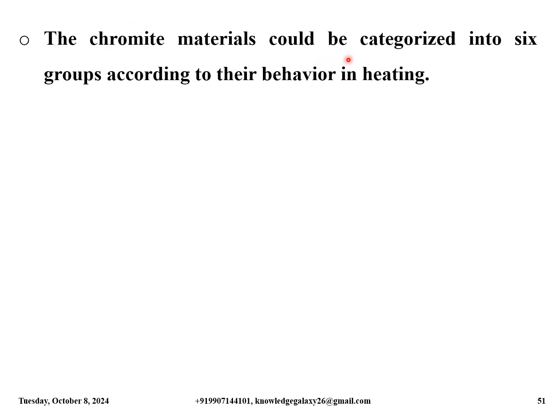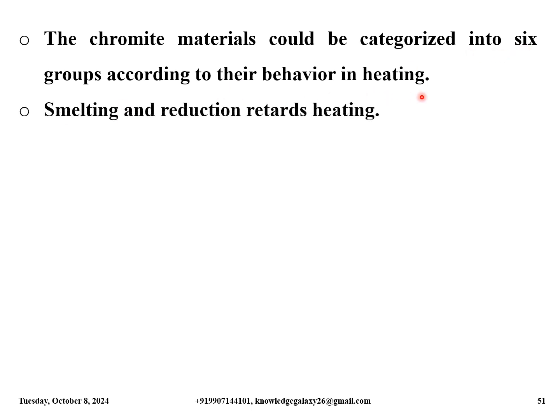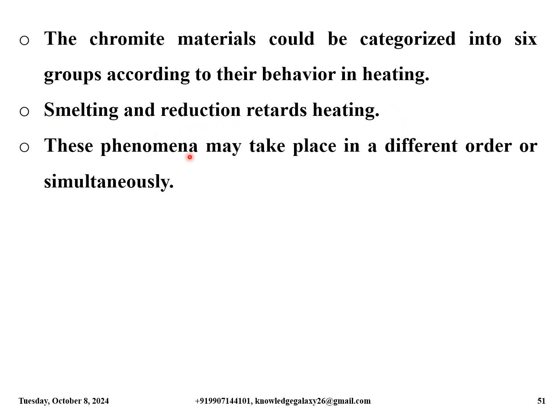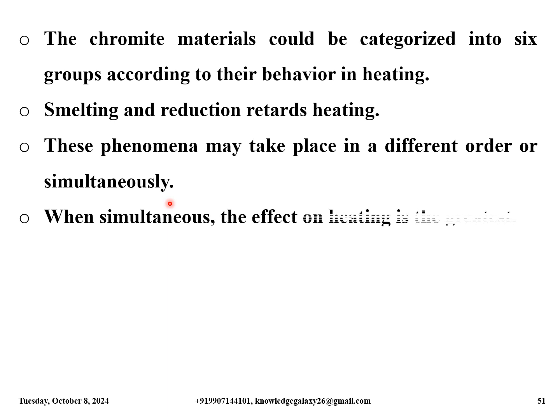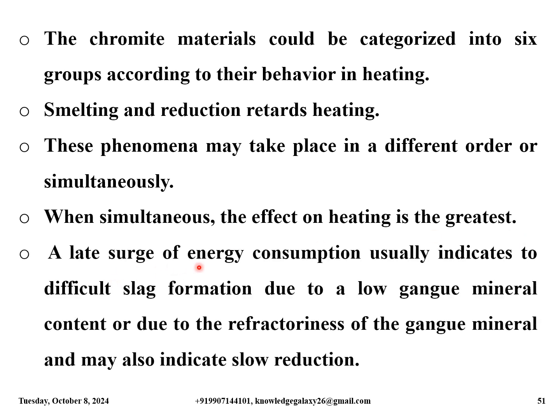The chromite materials could be categorized into six groups according to their behavior in heating. Smelting and reduction retard heating. These phenomena may take place in a different order or simultaneously. When simultaneous, the effect on heating is the greatest. A late surge of energy consumption usually indicates difficult slag formation due to a low gangue mineral content or due to the refractoriness of the gangue mineral, and may also indicate slow reduction.